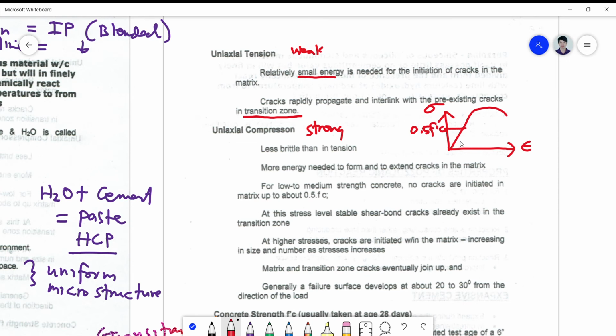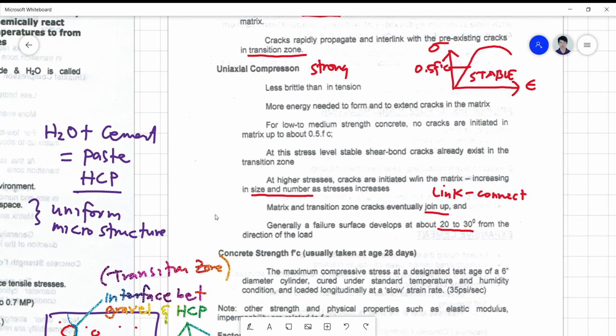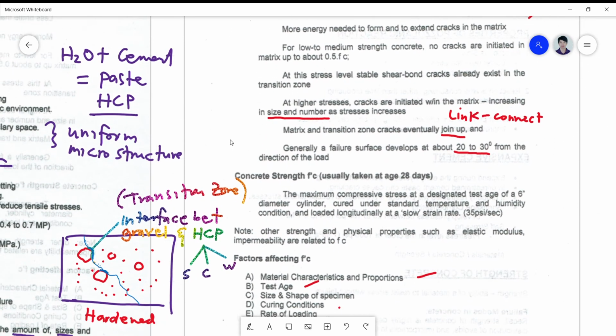So at this stress level, your concrete is said to be stable. Okay, stable shear bond. Okay, the transition zone cracks exist, but still your concrete is stable. At higher stresses, the cracks are initiated within the matrix, increasing in size and number. And the matrix and transition zone cracks eventually join up. So there is linking, no? It will link, interconnectivity. So link or connect, no? So your micro cracks will connect with your transition cracks, your capillary voids will join, and suddenly a general failure surface will develop at around 20 to 30 degrees from the direction of the load. So that's how uniaxial compression behavior emanates in the